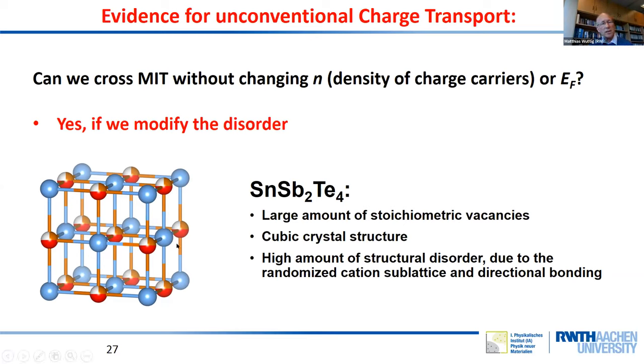These materials, as you can see here, have a cubic atomic arrangement. It's octahedral, like a rock salt structure, and there's a large amount of stoichiometric vacancies. You can imagine tellurium has one sublattice, and tin and antimony are on the other sublattice. So there's a large amount of vacancies, one vacancy per 4 tellurium atoms. These vacancies are stochastically distributed on this sublattice here, occupied by red, orange, and white.